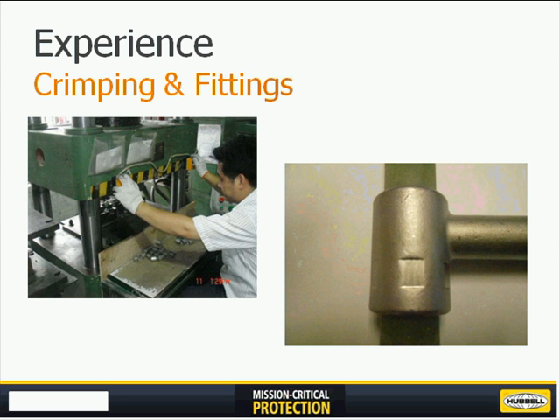This allows, again, elimination of rod cracking, and it also gives the fittings a very high pull-off strength that, of course, needs to be withstood during a Series 1 interruption, which is a higher current fault interruption. Forces and loads can be very high on the end fittings, of course, during this test, and so a good crimp is required to maintain integrity of the unit following an interruption.